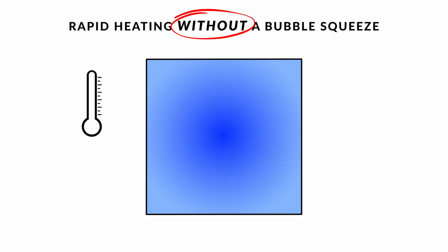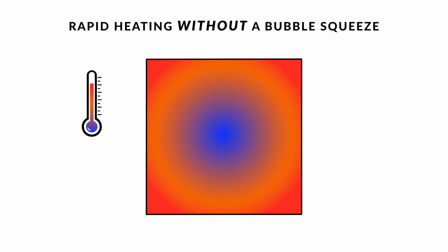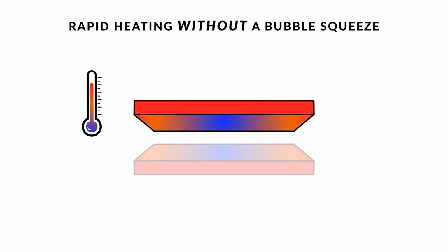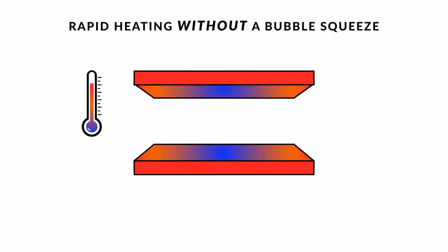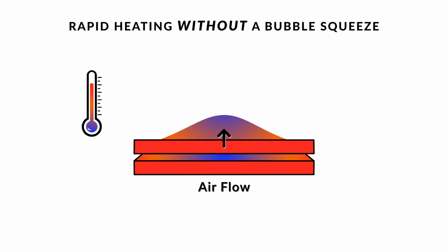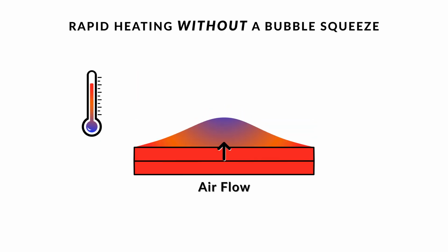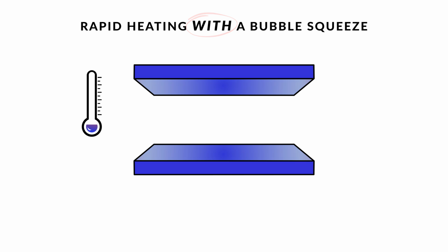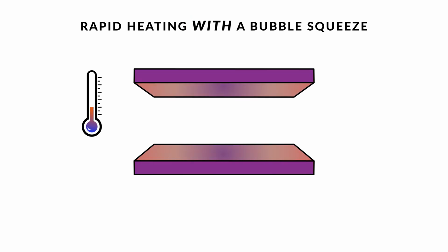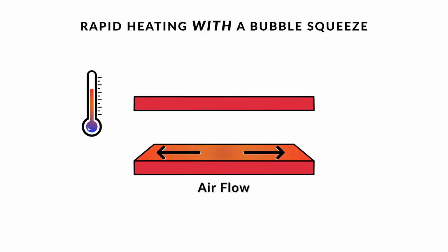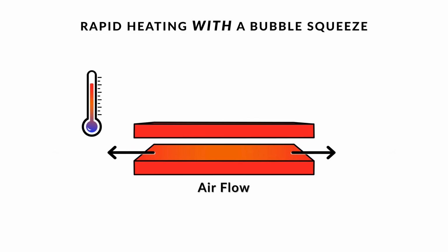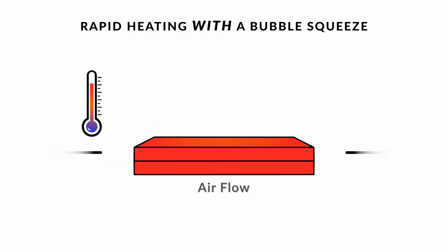When glass is heated rapidly, its outer edges will soften before its interior does. This means that the outer edges of the top layer of a multi-layer project will fuse down onto the layer below before the center, trapping air in between the two layers. A bubble squeeze slows the initial heating of the glass in order to give the upper layers enough time to evenly settle down onto the lower ones, thus allowing air to escape laterally from between the layers.